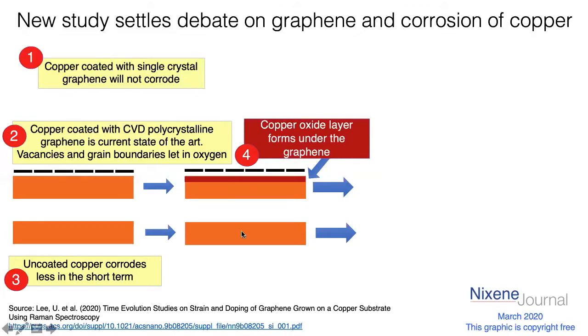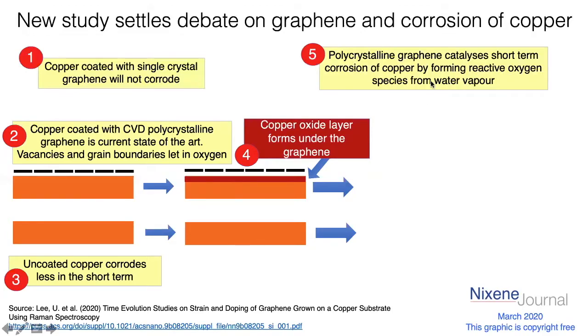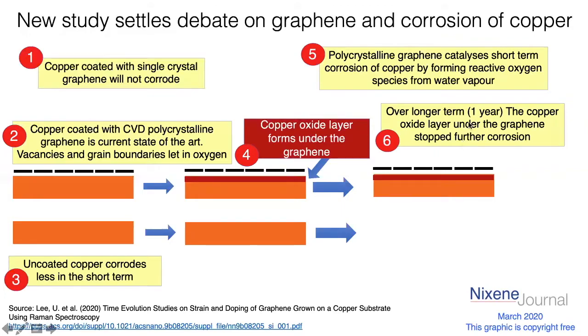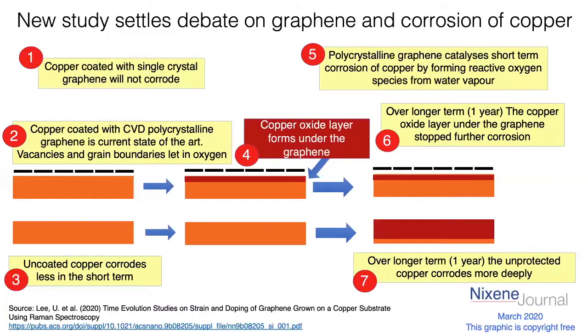Yeah, it's important that graphene is transparent. So what's going on here is that in the short term, graphene is acting as a catalyst and getting this copper oxide layer to form more rapidly. Now, what the study found was that over the longer term, and they looked at this over a year, once you've got this copper oxide layer forming underneath the graphene, that acted like a barrier to further oxygen. No more oxygen could get in past that initial oxide layer, and it stopped any further corrosion. Whereas unprotected copper actually did corrode more deeply and just kept on corroding and corroding until the copper was all gone.